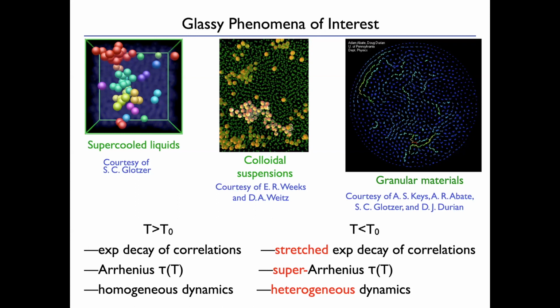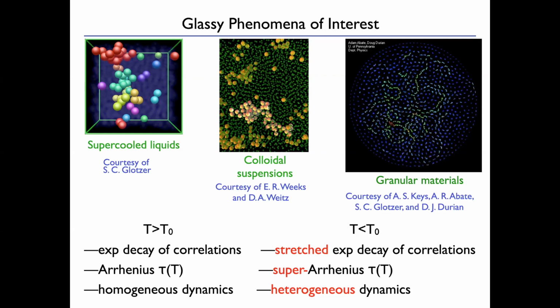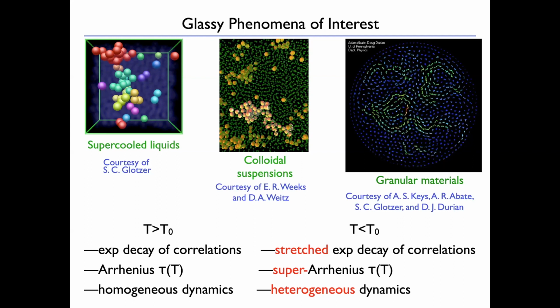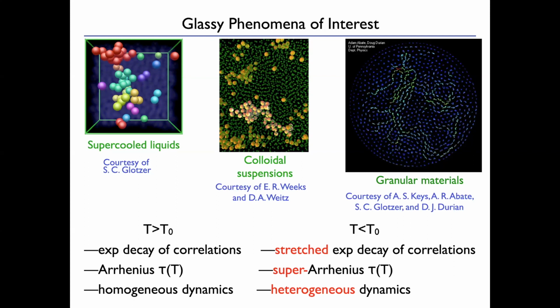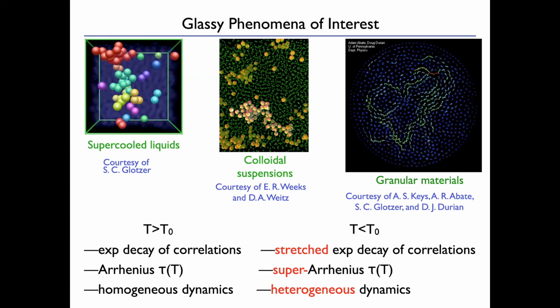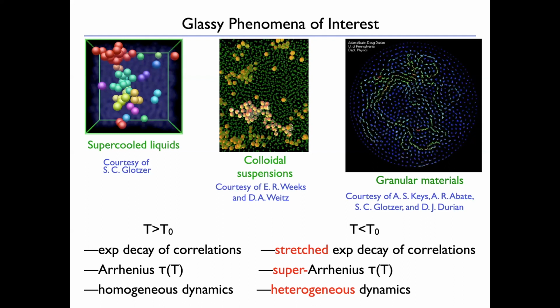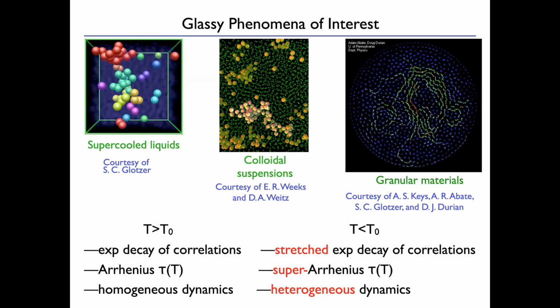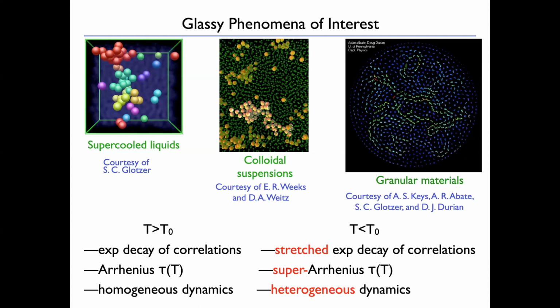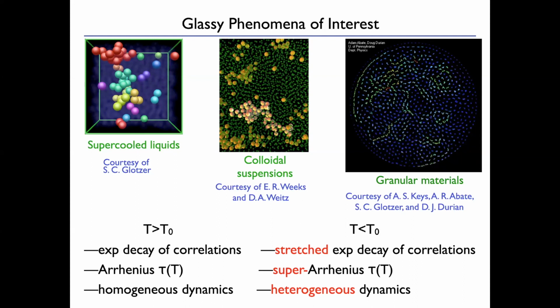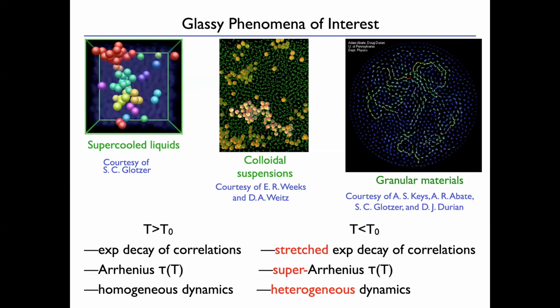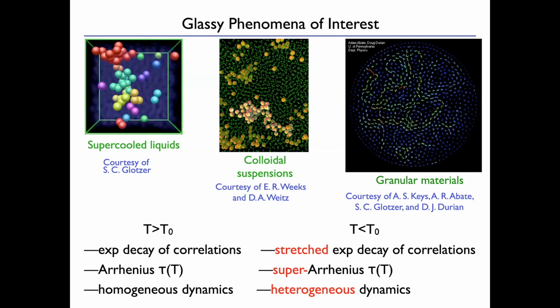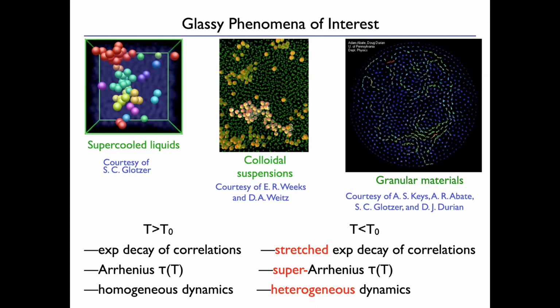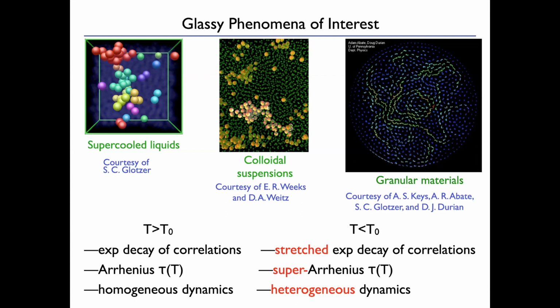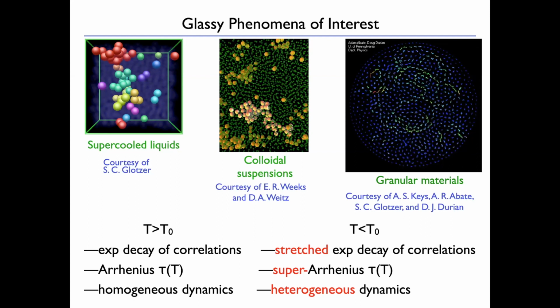It's actually very similar physics to what happens in a glassy system. And this on the right is just a movie of a granular system. This is actually an experiment where the particle tracks are shown, and they are labeled by color according to how far they moved in the relaxation time. So red is far and blue is not far. Okay, so the red tracks are long and the blue tracks are very short. So that's an example of this kinetic heterogeneity. So that distribution of how far they move becomes very non-Gaussian, broader as you lower the temperature, but it is Gaussian above the onset temperature, okay? So the dynamics are homogeneous above the onset temperature. They become heterogeneous below the onset temperature.